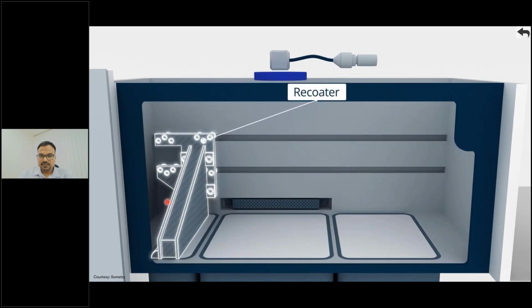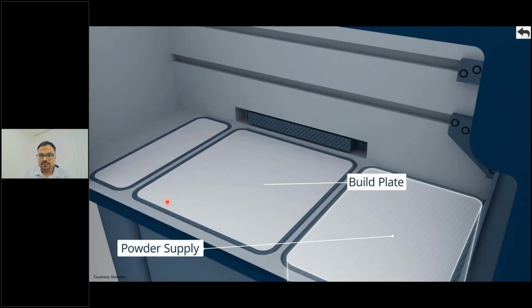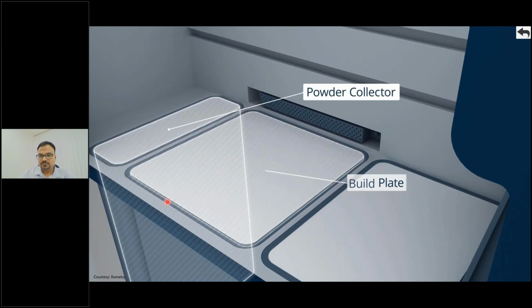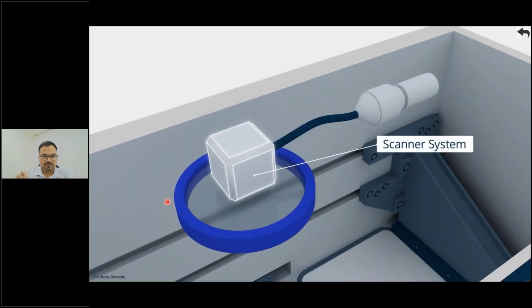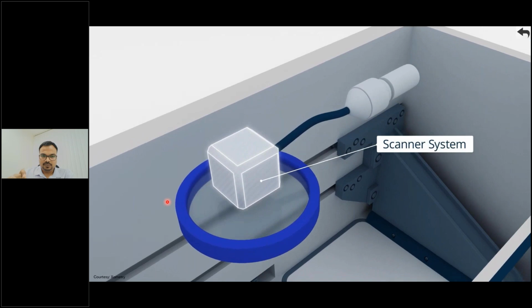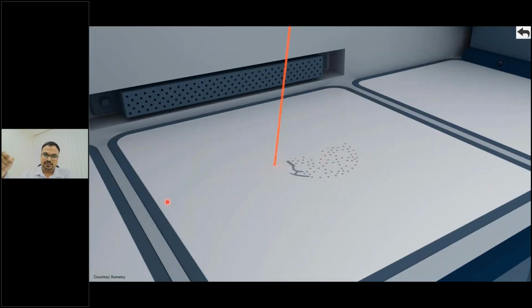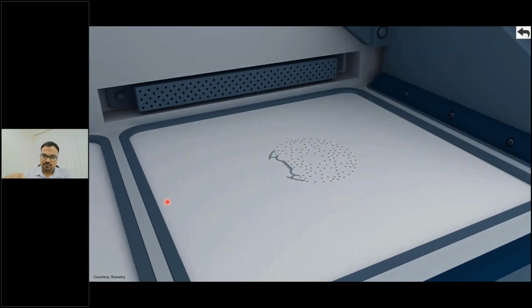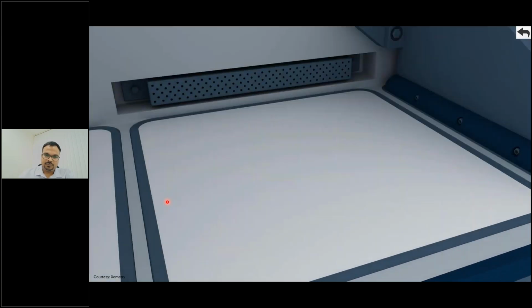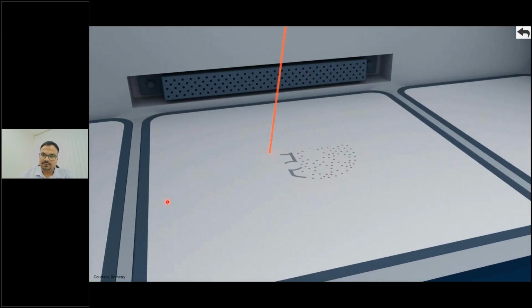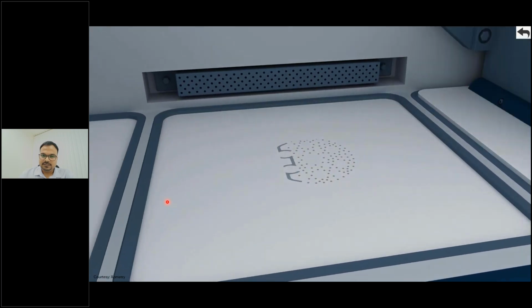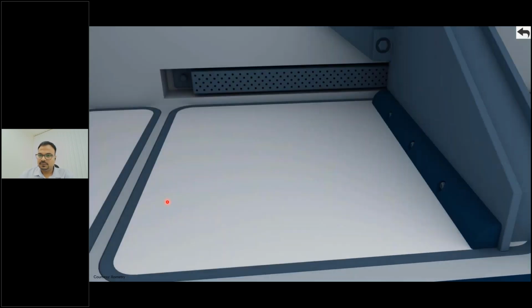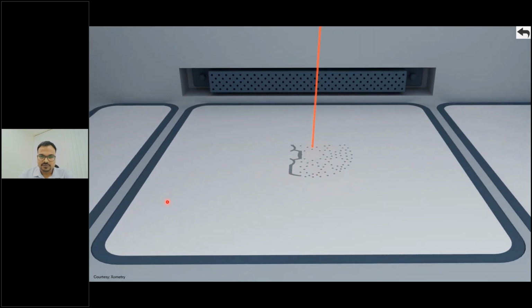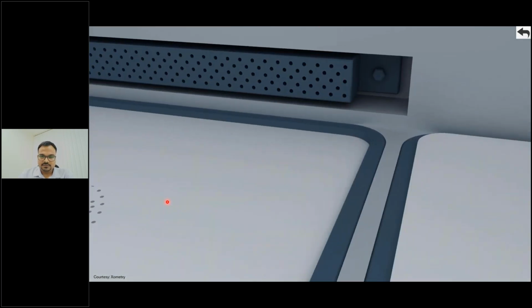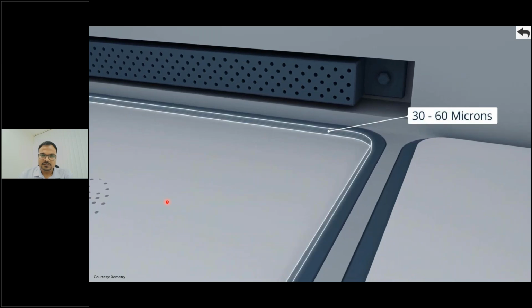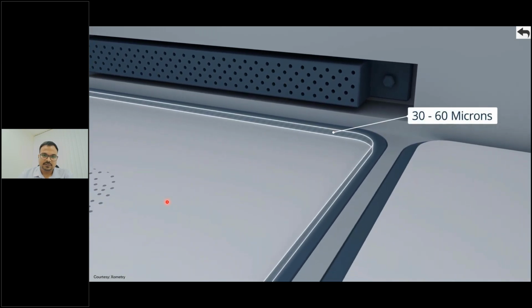So as I said, it happens inside the inert atmosphere like argon or nitrogen. So the powder is fed from the bottom to top, and the recoater recoats the powder in very fine layers as it is a powder bed fusion. And just on top, it has a fiber laser which actually melts the powder completely. More than 99.5% to 99.6% density is achieved across aluminiums, and in steels you get 99.7% to 99.8% densities in your tool. So these are completely solidified materials that you get out of this printer.